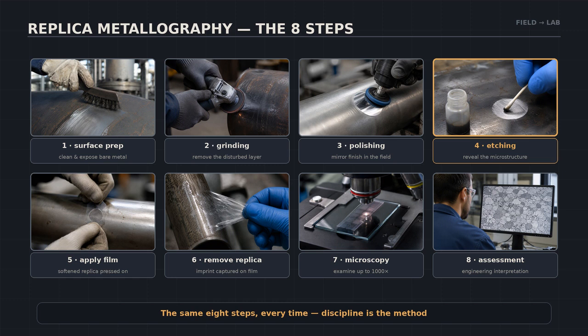Now the clever part, a softened acetate film is pressed onto that etched surface. It flows into every microscopic detail and hardens into a perfect negative. Peel it off, and the replica carries the microstructure back to the laboratory. Under the optical microscope, at up to 1,000 times magnification, you read the material like a book. And step 8 is the one that matters most, engineering assessment of what you found.